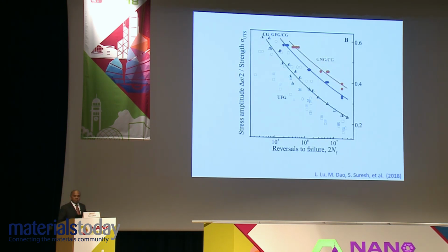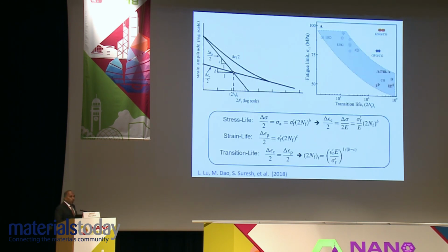So what is the benefit of this? For crack initiation, the endurance limit, stress amplitude normalized by strength in terms of reversals to failure, if you look at ultra-fine grain, coarse grain, or fine grain and graded, coarse grain graded, this is the endurance limit curve or stress life curve. But when you have a surface nano gradient, this is the best response of them all with respect to stress life fatigue. If you go to strain life fatigue, of course you have, this is stress life fatigue, this is strain life fatigue. If you add that, you get the total response.